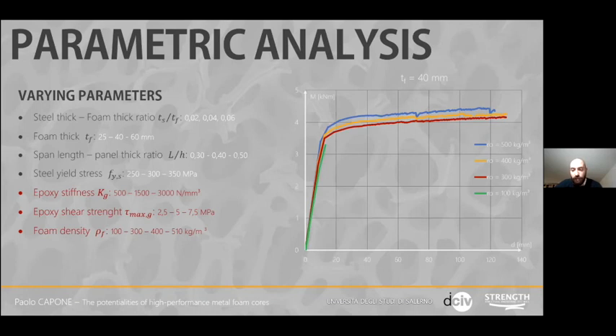Regarding the foam density, literature equations have been used to model cases with density lower than 110 kilograms per cubic meter. The foam controls the shear failure of the sandwich panel. The numerical results indicate the possibility to adopt lower density foams for the application of the SAS panels in floors. The most interesting thing confirmed by both the numerical and analytical modeling is that it would be possible to reduce the density to a value around 100 kilograms per cubic meter.